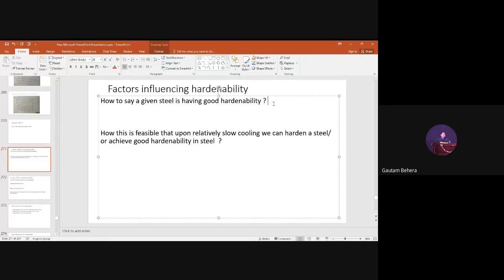But the condition applied, the thickness, is important also. That's why I told you the thickness is a factor influencing hardenability. If you have a very high thickness, then you cannot achieve good hardenability characteristics up to the center, because the center will have a maximum amount of pearlite, or you can have 100% pearlite, and pearlite is a softer phase compared to martensite. So this is the concept.